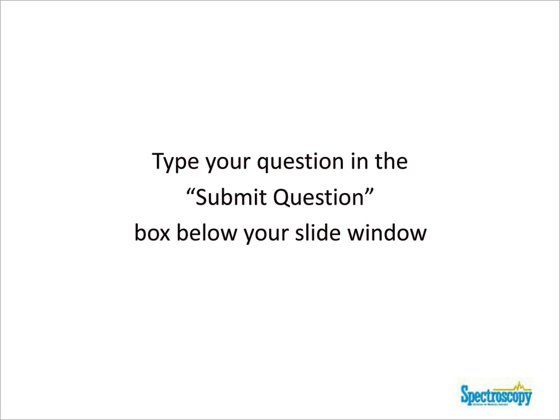Great. Chatty, how long does the analysis take using single particle ICP-MS? Well, it all depends on the particle concentration or what you're trying to achieve from your analysis. Ideally, in most of the application notes that we're currently running, we use a minute or so. Sometimes if we have a high particle number, 30 seconds is usually sufficient to get you a proper statistical distribution for your nanoparticles. But if I want to put a number on it, I would say it's definitely less than a minute. In some instances where you have only a few particles in your solution and you want to build the statistical information about the particles in that solution, you might want to acquire data for a longer, extended period of time. But really, it's usually less than a minute.